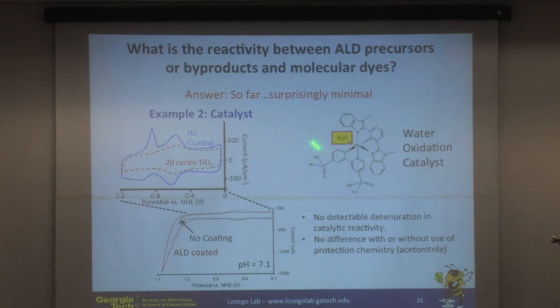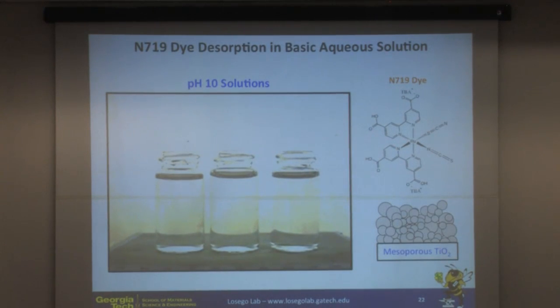And likely what's happening is that we're dehydrating the catalyst prior to doing ALD, because the ALD is being done in a vacuum environment, essentially no water environment. So we're driving that water molecule off prior to doing the deposition. So this is an example here.